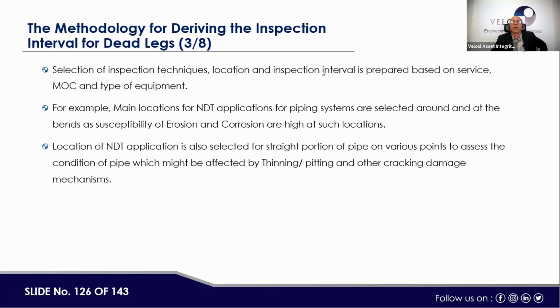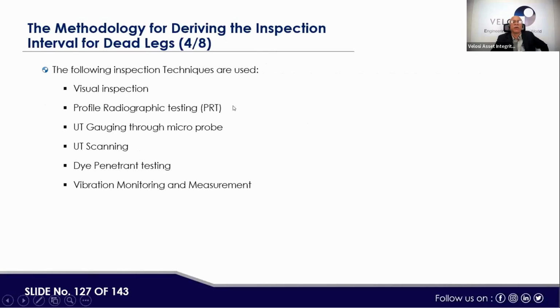Then the selection of the inspection technique, location, and inspection interval is prepared based on service, MOC, and type of equipment. For example, the main locations for NDT application for piping systems are selected around and at the bends, as the susceptibility to erosion and corrosion is relatively high at these locations. Locations for NDT are also selected on the straight portions of the pipe at various points to assess the condition of the pipe, which might be affected by thinning, pitting, and other cracking damage mechanisms. Then the following inspection techniques are preferred: visual inspection, profile radiography, UT gauging through microprobe for the small bore, UT scanning, dye penetrant testing or DPT, and vibration monitoring and measurement for small bore.